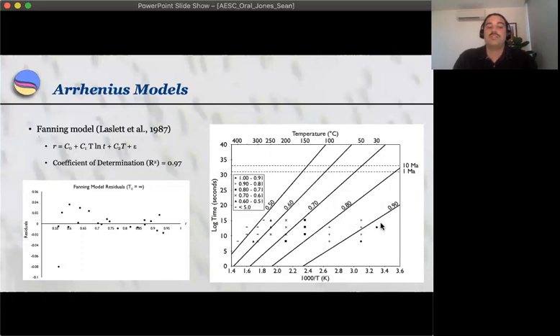Based on these positions of the contours at geological timescales, the model shows that a significant reduction in the etchable lengths of the fission tracks takes place at ambient and lower temperatures, suggesting that monazite is particularly sensitive to low temperature thermal annealing. We then see considerably more track shortening occurring in levels that would be of the shallow upper crust between temperatures of about 50 to 160 degrees over the same time period. And then we see complete annealing of the fission tracks occurring very rapidly when the equivalent confined track length reduction decreases below 0.5.